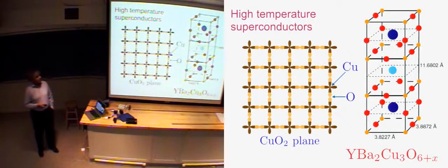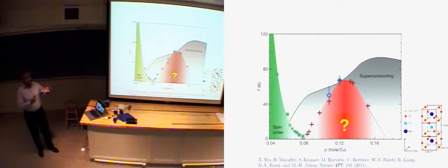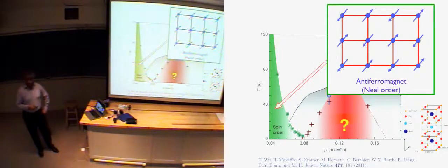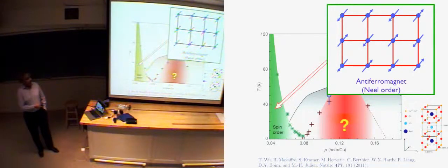If you now look as a function of density, this is one version of a phase diagram of YBCO, which summarizes the basic points I want to focus on in this talk. First of all, when you have very low hole density — meaning exactly one electron for each copper — then you have an antiferromagnet where that electron on the copper forms this checkerboard-type pattern. Everybody agrees with that. In YBCO, this lasts only for a small range of doping and will not play any direct role in what I'm going to talk about.